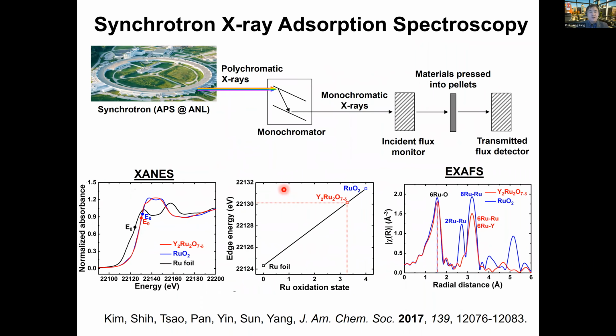So we looked a little more carefully at what happened in this particular system, in terms of the valence of the ruthenium site. We did X-ray absorption spectroscopy, examining the near edge, and also the EXAFS. From the EXAFS, we know that if you compare, we do not have major differences. But if you look at the valence state in the pyrochlore catalyst analysis, referenced to the zero valence of ruthenium foil metal versus ruthenium oxide, we actually find it somewhere in between. That means we have non-stoichiometry of the ruthenium site. Okay, that has always been indicated as a catalyst with higher activities.